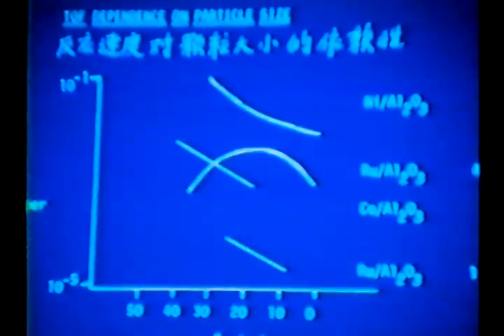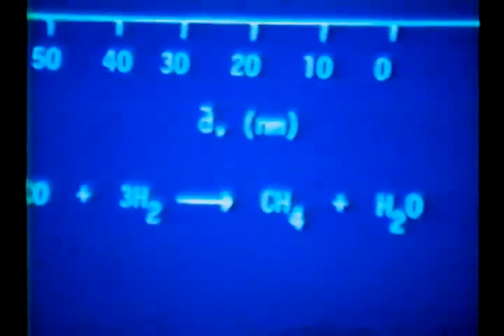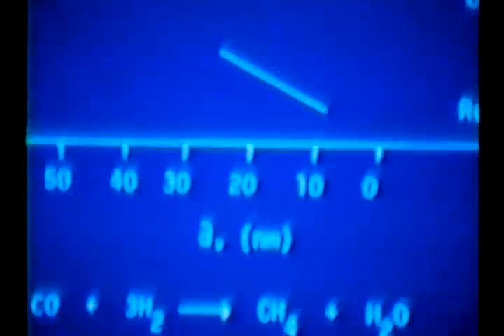Well, if you look in the literature and you make a series of curves like this, and we've taken these from like 4 different papers, and look at the turnover frequencies, the number of molecules of methane produced from carbon monoxide and hydrogen per site per unit time as a function of particle size. And this is usually what's not readily available, the particle size and the turnover frequencies. If you do that and you look at lots of different reactions, what you can see is for nickel on alumina, the turnover frequency basically goes down as a function of particle size. Cobalt goes down, ruthenium at 1 atmosphere goes down, ruthenium at 4 atmospheres looks like it maximizes.